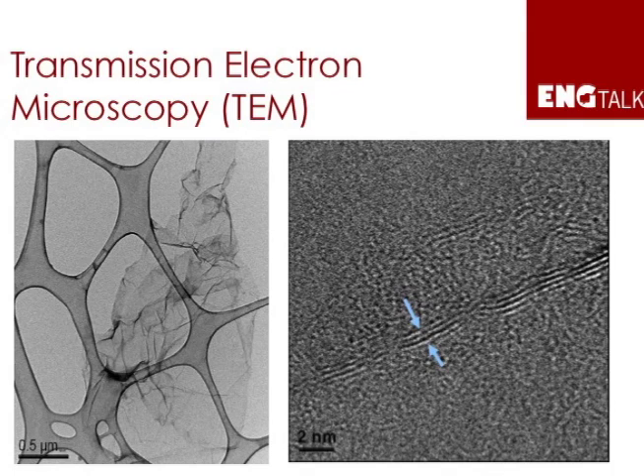After making graphene by the top-down method, we can see it under a transmission electron microscope. What you find is that the graphene sheet dimensions are of the order of microns, but its thickness is of the order of one to two nanometers. So we end up with three to four layer graphene platelets — we don't get individual graphene sheets, though we'd love to.